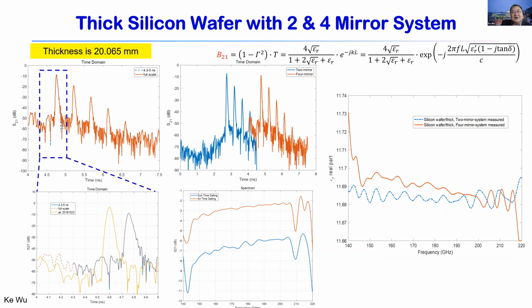So this is the measurement result port to port from the S-parameter values. Of course, you cannot see anything here, you look at these spikes and so on. But through the parametric extraction technique we developed, we are able to see clearly the real part of the permittivity of these silicon wafers. These are thick wafers for 2-mirror and 4-mirror system measurements. You can see they agree pretty well, and we know roughly the value is about 11.6 to 11.8, depending on the density of the silicon. If you have high quality or highly resistive silicon, you end up with slightly different values, but about 11.67 gives us very good satisfaction. So these are the 2-mirror and 4-mirror system results.